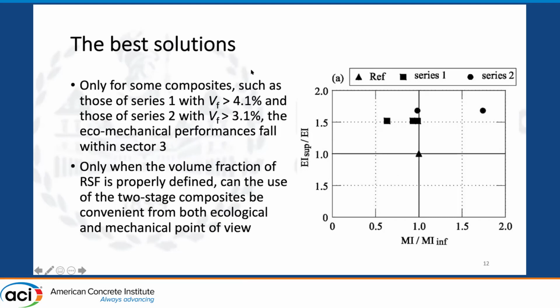And these are the results of our eco-mechanical analysis. As you can see, here we have the reference 1, 1, and then these squares are the results of series 1. As you can see, we reduced the impact of the reference system, but to reach sector 3, this one, where we have the best ecological and mechanical solution, we need in series 1 at least 4.1% in volume of steel fibers. Then here you have the results of series 2, where you are in field 3 when the content of recycled steel fiber is larger than 3.1.